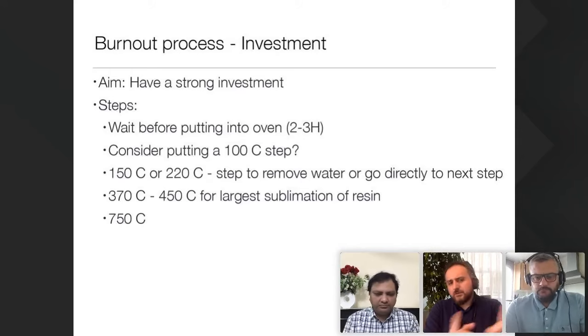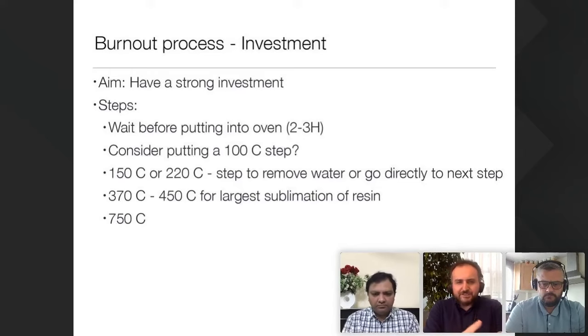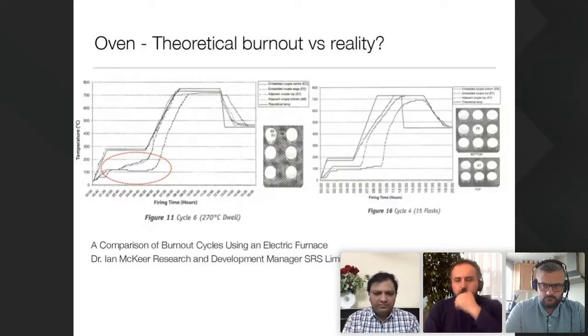Then remember there was this safe zone between 370 and 450 degrees, where the investment is not basically expanding. That's also a good thing because this is where most of the resin is disappearing. So you can use that safe zone as a step and leave the investment there. Then you go to 730 or 750 and finish your casting, right?